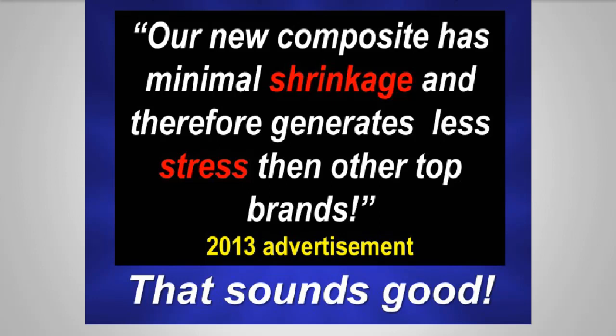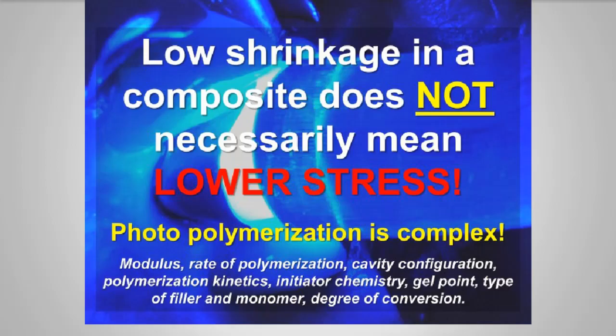But I think we all need to be very, very careful, because as good as that sounds, we need to understand something. Low shrinkage in a composite does not necessarily mean less stress is transferred to the adhesive interface. Photopolymerization is very complex, and many other factors, some of which we see listed down here, also have a very profound effect on polymerization shrinkage stress development. And it is very possible, by the way, to have a composite that shrinks less than another, but still induce more stress at the adhesive interface because of all these other factors.